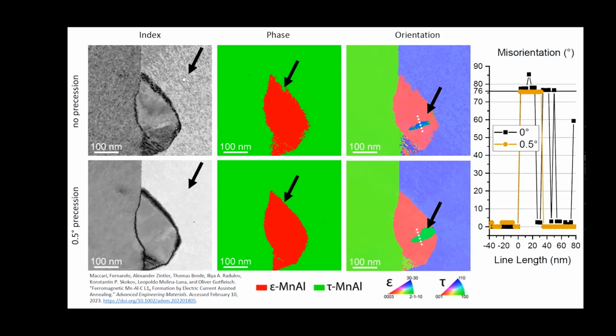And once we turn on precession, and this is with a precession angle of 0.5 degrees, the noise is basically gone, because the quality of the diffraction pattern improved so much that the software has a much easier time deciding on which phase and which orientation to match to the experimental diffraction. And you can see the same thing in these phase maps. And as I explained earlier, we have this epsilon phase grain here in red inside this matrix of the tau grains. And this is displayed quite nicely. And as you can see, with precession turned on, the interface is also much sharper than on the grain that you see here on top with no precession turned on.